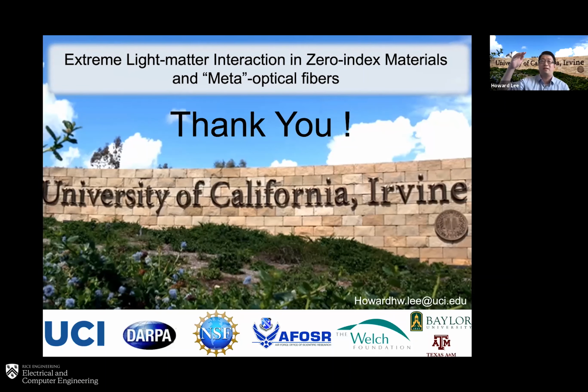But certainly if you are able to find an even lower loss material, your nonlinearity could go up quite significantly, or even all the effects we have been talking about. So this is something quite exciting. That means if we can find some low loss ENZ material, you can maybe enhance by a couple of orders of magnitude as well. So tuning that is possible as well. For example, when you're tuning the electron density, you actually can tune the losses as well. But there are some other materials, and this is something we're also exploring, to find a material with maybe even lower loss, that could find more applications.